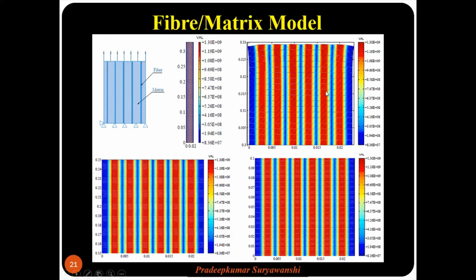Now it is clearly seen from these enlarged diagrams that there is a large variation in the stress when you consider matrix and fiber. And as expected, fiber has taken up most of the stress, and stress is very high as compared to the matrix. These results are in line with the experimental results as well as results presented in the literature. Okay, so we'll move on to the next slide now.